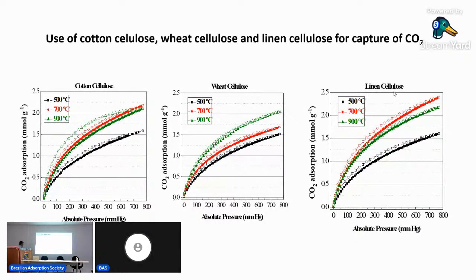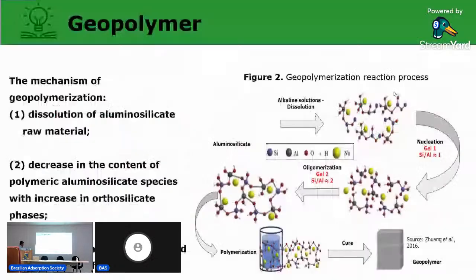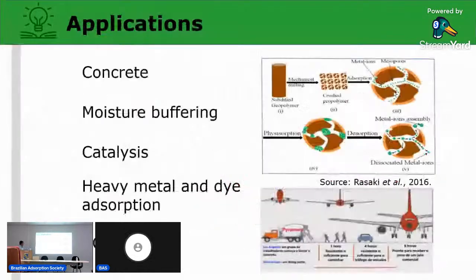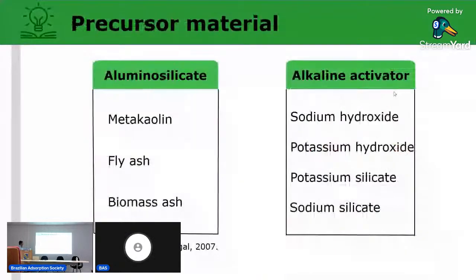geopolymer is a very easy process, the preparation with low-cost reagents, and it's possible to use this geopolymer in applications like concrete, moisture buffering, catalyst, heavy metal adsorption, and finally carbon dioxide capture. And here, such as metakaolin, fly ash or biomass ash. There are very different biomass ways for the preparation of this absorbent.